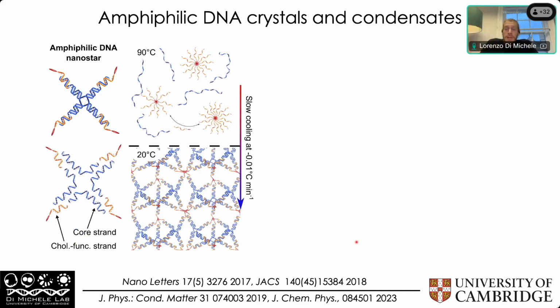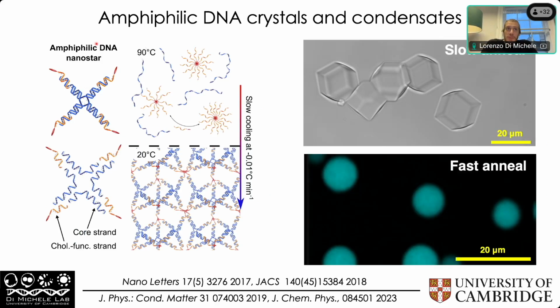So in my group, we did a little bit of work on this over the years. We introduced a slight variation on the theme of these DNA nanostars by replacing these DNA sticky ends that interact through base pairing with some non-specifically interacting hydrophobic molecules, in particular cholesterol molecules. And other than this, these objects behave in a quite similar way. Perhaps the most prominent difference between these cholesterolized nanostars and the regular ones is that the cholesterolized nanostars actually can form crystals. That's because the cholesterol molecules actually bind to many cholesterol molecules. So you have an extra element of multivalency there, if you want.